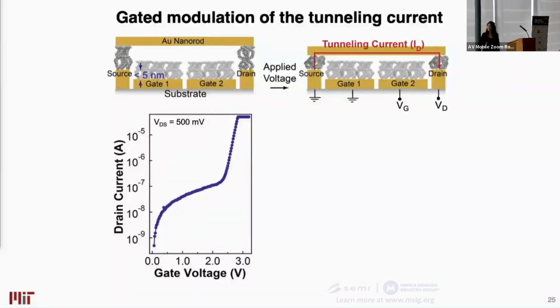If I zoom in, you can see how the molecular gap is well defined. And if we test it, we do get the modulation of the current that we expect for these devices. Initially, you see an exponential increase in the current as the switching gap shrinks when you apply a voltage. That is followed by an abrupt increase in current, associated with the typical pull-in process, where your attractive forces overwhelm the restoring forces, so your top contact accelerates towards the bottom. And this final section is just a limit set by the measurement tool that we're using.